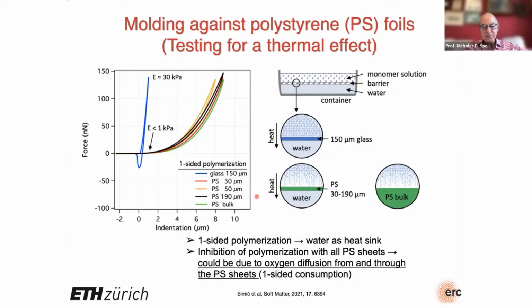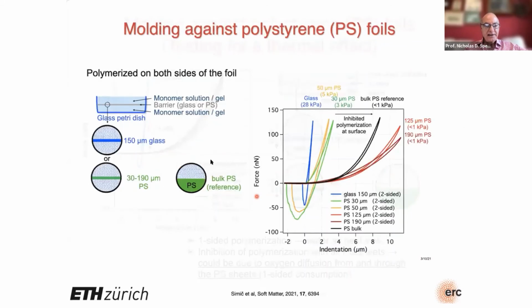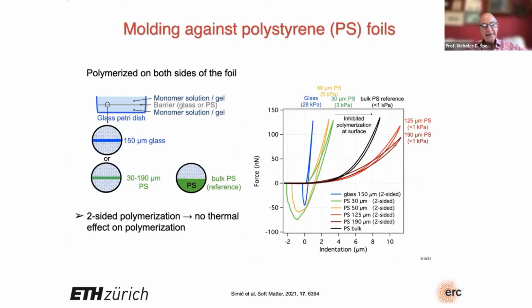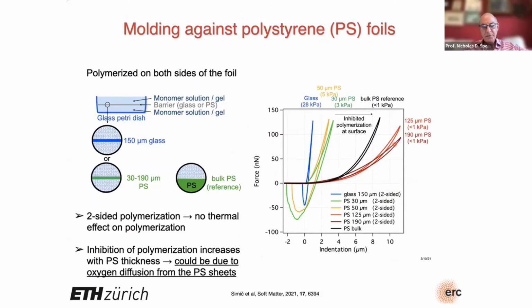We thought maybe it's oxygen diffusion from and through the polystyrene sheets. The way we tested that was doing two-side polymerization with different membranes. And we found that the thicker the polystyrene membrane, the softer the surface. In other words, that was pretty clear evidence that although there was no evidence for a thermal effect, the more polystyrene we had there, the more dissolved oxygen was present and could diffuse out towards the polymerizing gel, the softer the resulting hydrogel, so the more dangling chains.